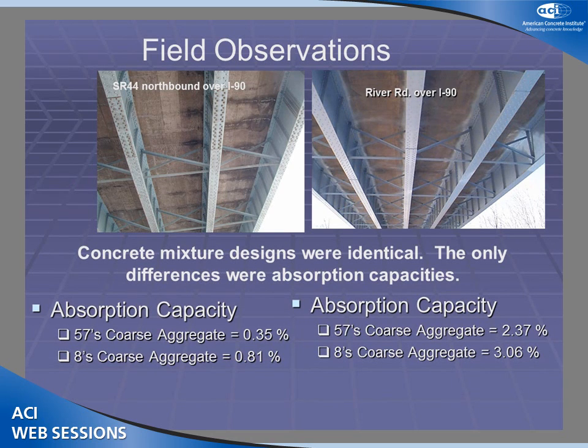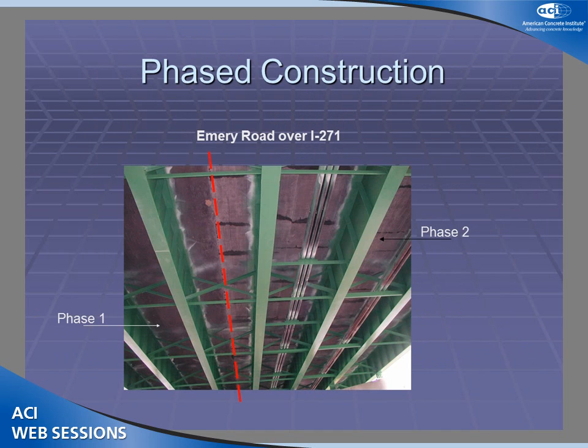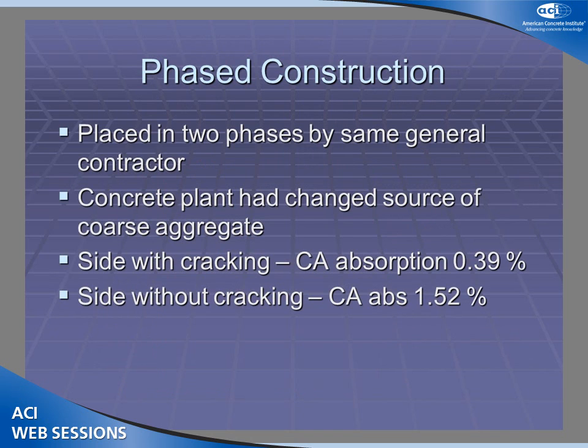And this theory was probably best illustrated or best confirmed in a project that had staged construction. So you had the same bridge, you had the same contractor working on the bridge, and half of it cracked and the other half did not. So what changed? You got the same contractor, you got the same mixture proportions, same phase. However, the concrete plant had changed the source of the coarse aggregate in between those two phases of construction. And so the side that cracked had a relatively low coarse absorption, and the side that did not crack had about 1.5%.